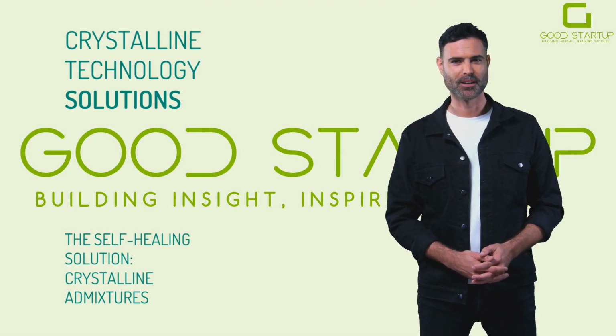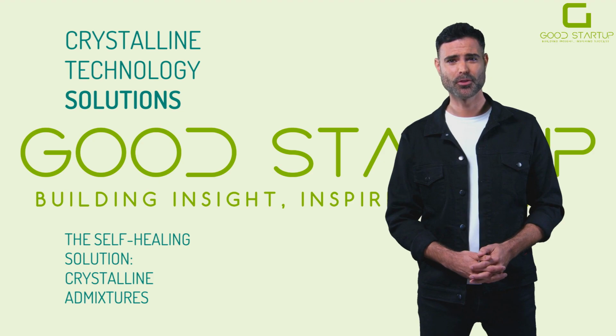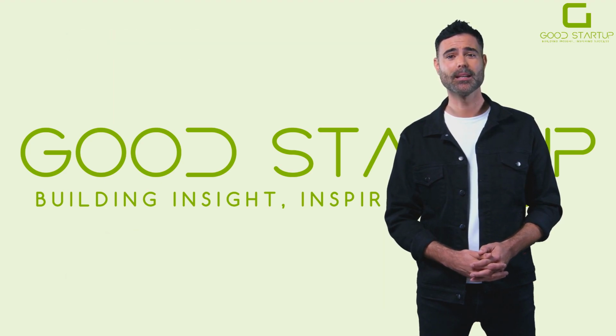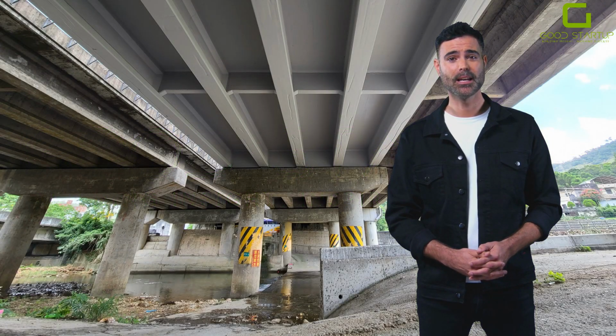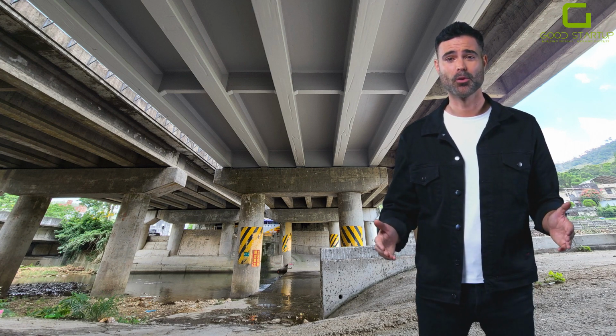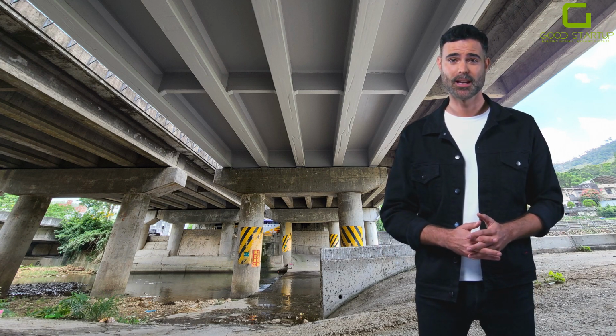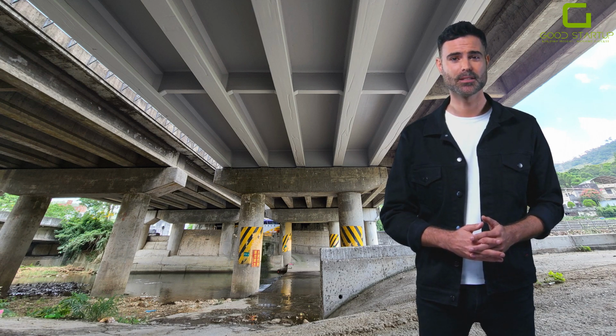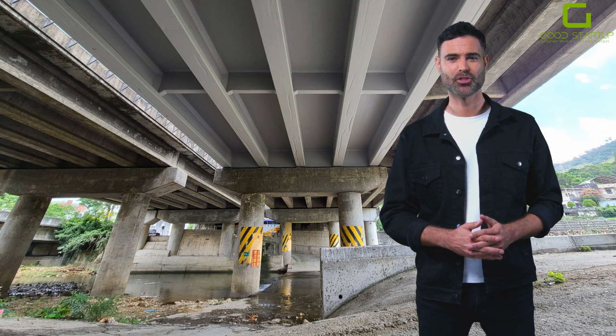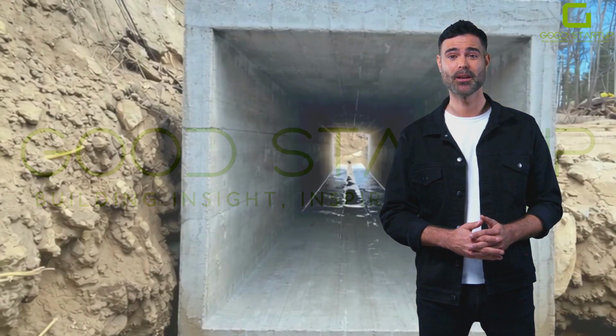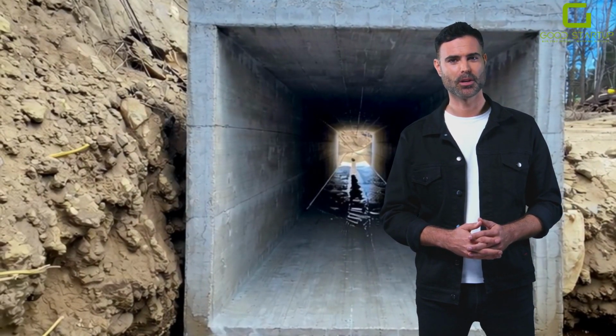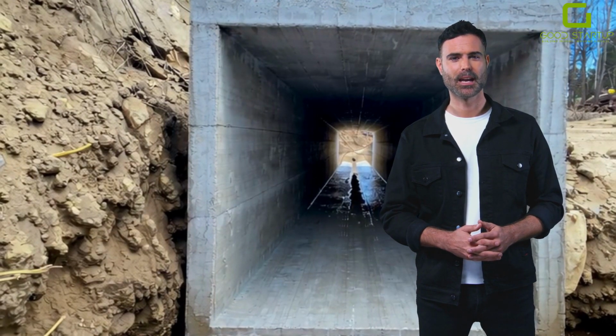Of course, it's not just about healing cracks. Even uncracked concrete benefits from reduced permeability. Crystalline admixtures fill the inherent porosity of concrete with crystal growth. Independent studies show marked reductions in water absorption and permeability. In fact, a review of many tests found that hydrophobic and crystalline admixtures can cut water absorption by up to 80%. Air permeability, which correlates with how easily aggressive agents penetrate, can be reduced by 55%. In one study, adding a crystalline admixture reduced concrete's water absorption rate and air permeability, significantly slowing moisture ingress. The concrete becomes denser and drier and stays that way throughout its life.